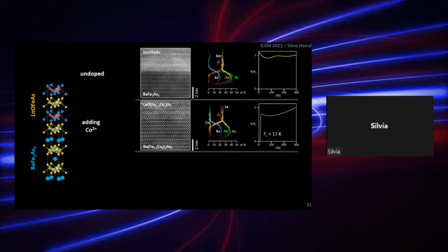However, we see that the cobalt diffuses from the top layer into the bottom layer down to the substrate and leads to electron doping as we know it from any bulk experiment. Finally, we also see that we can measure a TC of almost 17 Kelvin, so the cobalt concentration seems to be balanced within both layers.